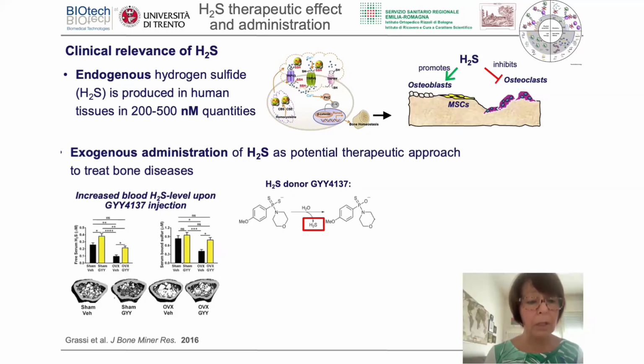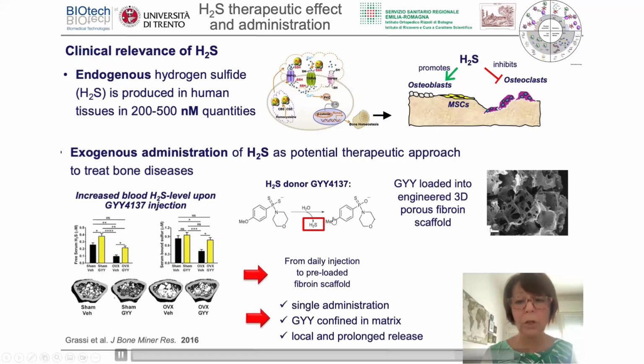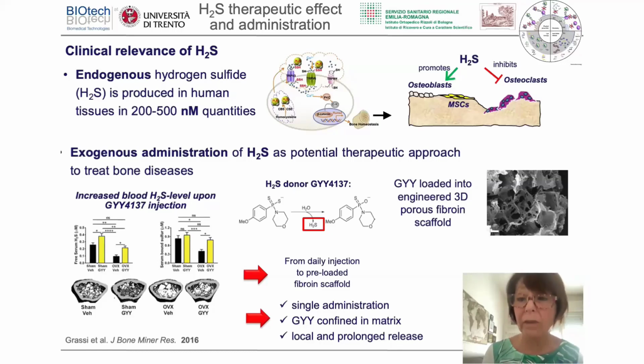The group of the Rizzoli Institute, Dr. Grassi, identified this sulfur donor, GYY, and at the beginning this was used at systemic level, injecting it into the osteoporotic animal, having a beneficial effect, but with the need of daily administration of this donor. So we moved to tissue engineering. In this case, this donor was combined with a porous structure made of fibrin, and we loaded it with the sulfur donor. The release was assessed, and the sulfur donor GYY was released completely in 12 hours.